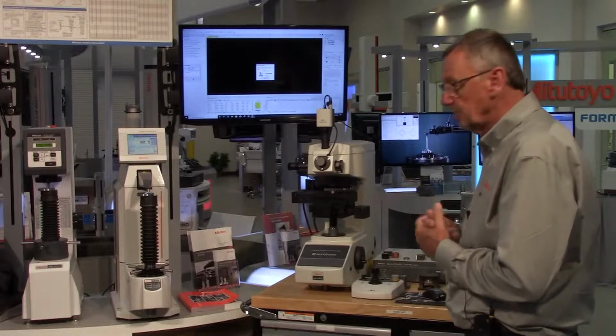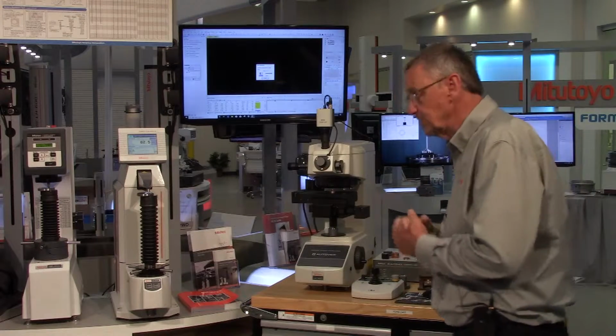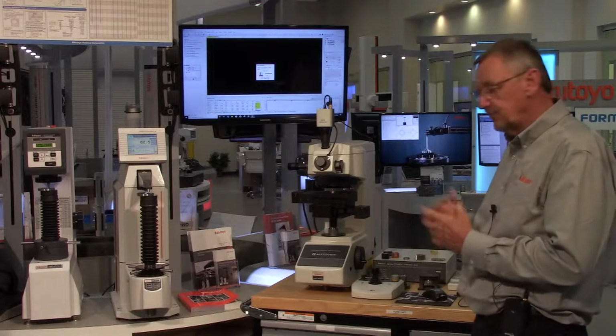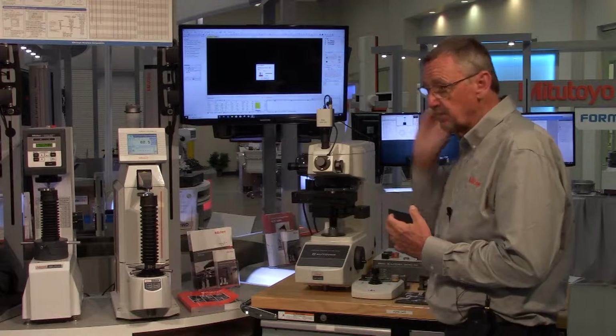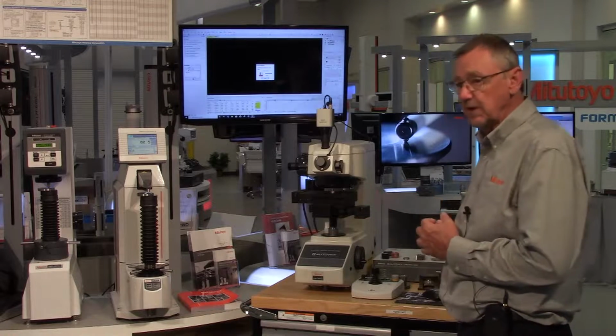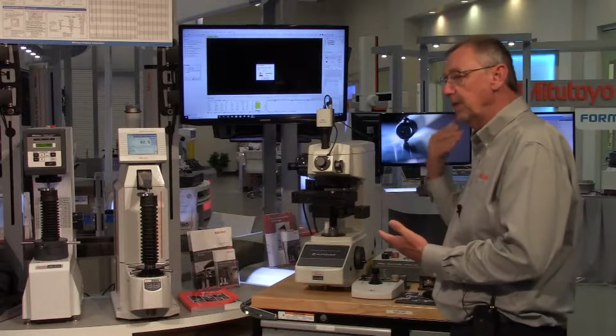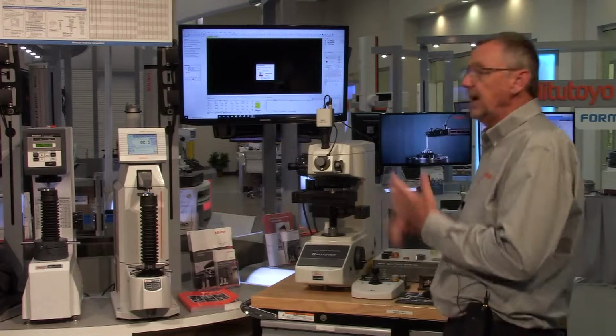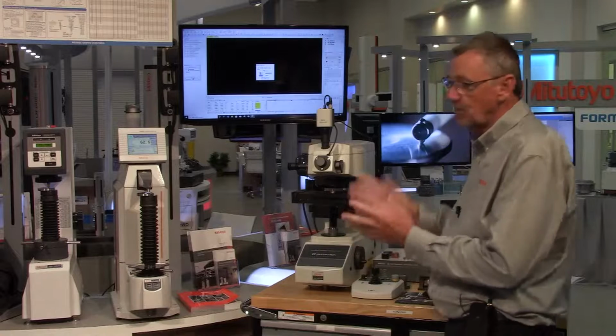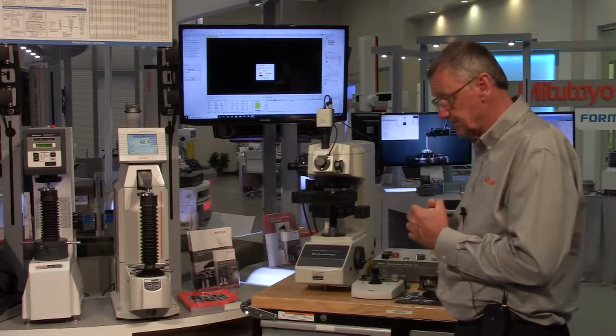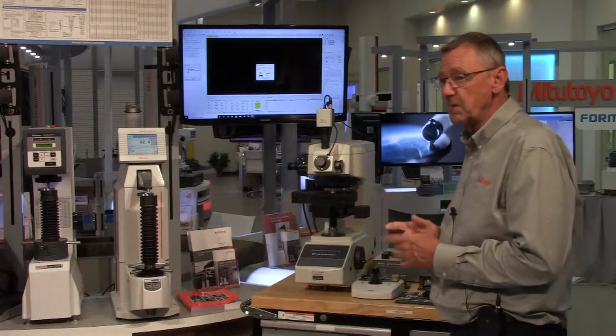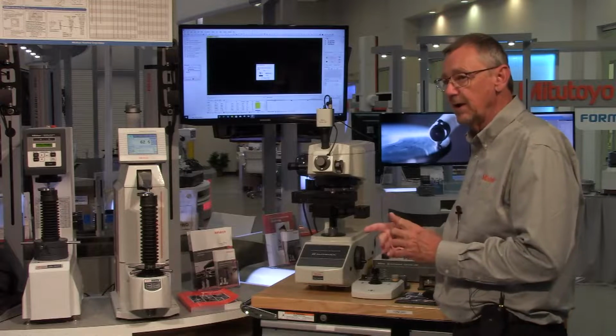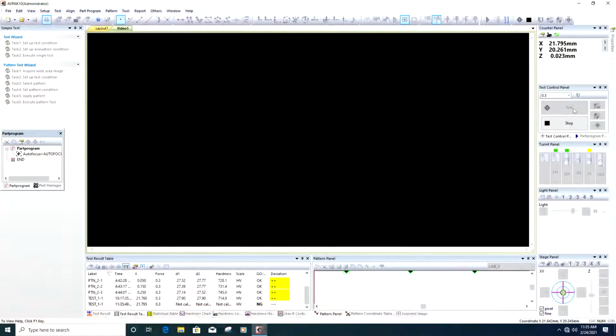And one of the reasons why automation is so popular for these machines is, according to ASTM and ISO and all the governing bodies, it can't be speeded up. The dwell times, the impact rate of the diamond into the part has to be 70 microns per second or less. The dwell times are 15 seconds or so. So it really can't be speeded up. So the reason they're automated is you can walk away, do a bunch of tests, come back and get your